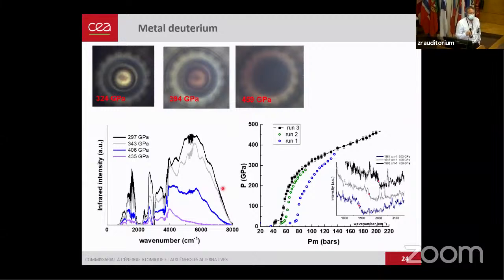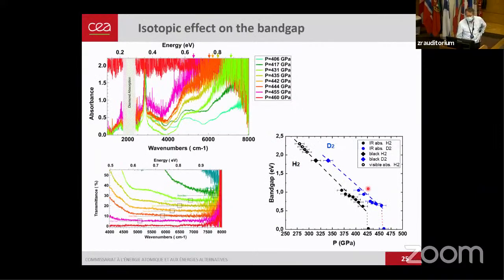But now we have to prove that this measurement is really reproducible, detailed and quantitative. So we redid this year the same measurements on deuterium. You have to go to higher pressure because of the isotopic effect. Again, we have nice infrared spectra, the same measurements, nice measurements of the pressure. We do the same analysis with the gap, and we see a strong isotopic shift on the gap. Deuterium is metallizing above hydrogen. You have to go to higher pressure to observe that, which is a true quantum effect.